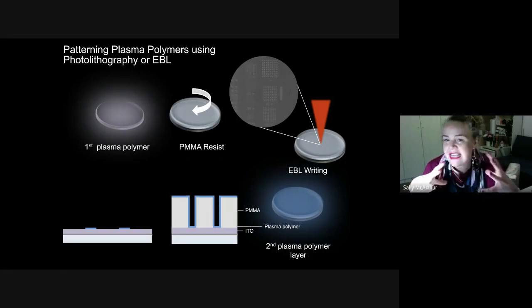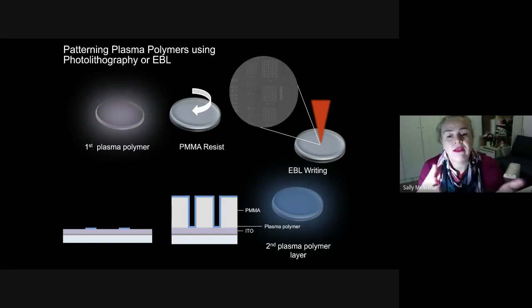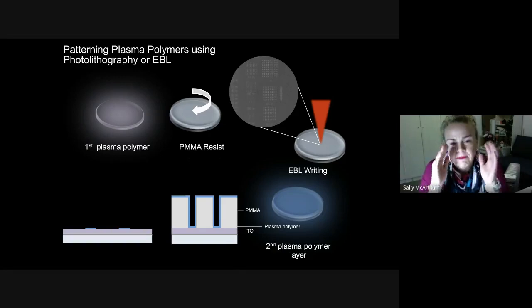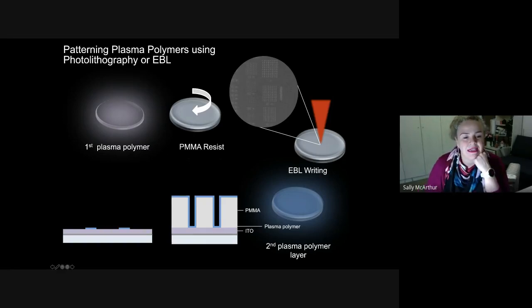So in this case, again, it's the exact same structure that we use with the photolithography, but we're using now a PMMA resist on our system and writing on the PMMA with the EBL. There has been work done where people have used the EBL to directly write onto the plasma polymer. So you can imagine the plasma polymer actually being a resist. But in our case, because we want two chemistries to be patterned and we're interested in the chemistries of the plasma polymer rather than the underlying material, we're doing PMMA resist, EBL writing, second plasma polymer on, and then we can create a pattern at the end here where we've got two plasma polymers patterned next to each other. But the EBL gives us the ability to look at how small a feature we can actually reproduce in this.